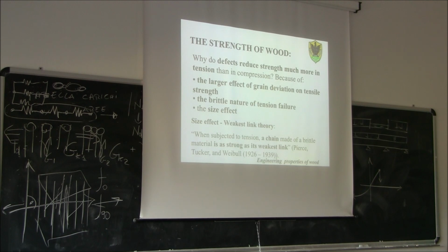The plastic behavior is motivated by the fact that the fibers of the S2 layer are not only vertical. They are squeezed together, like we said before. In compression, initially the fibers are spaced apart. Then when you start squeezing them, basically you fail the middle lamella, and in the end you get to a situation where these fibers are basically in contact. And they are strong. So for this reason, this curve keeps going, particularly in compression perpendicular to the grain, and also in compression parallel to the grain, but this is limited in some way by the local buckling phenomenon of the fiber.